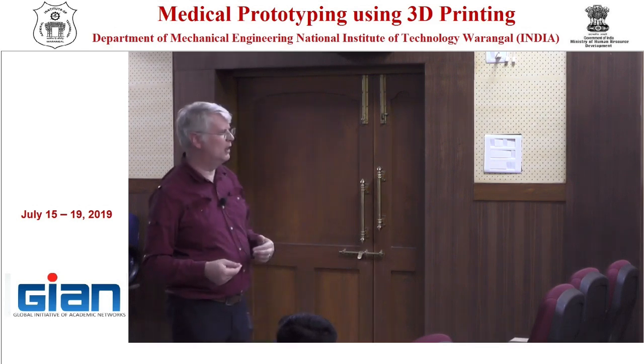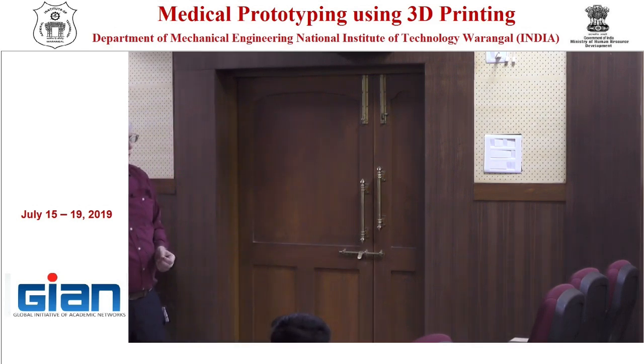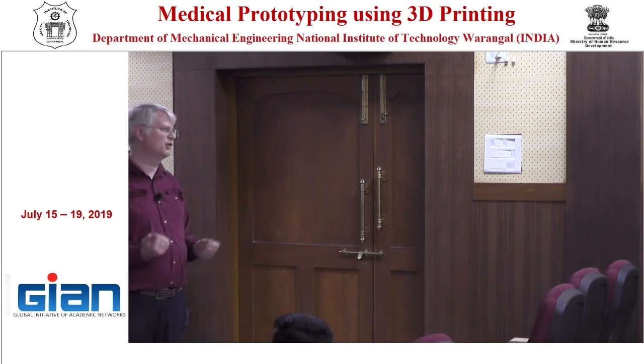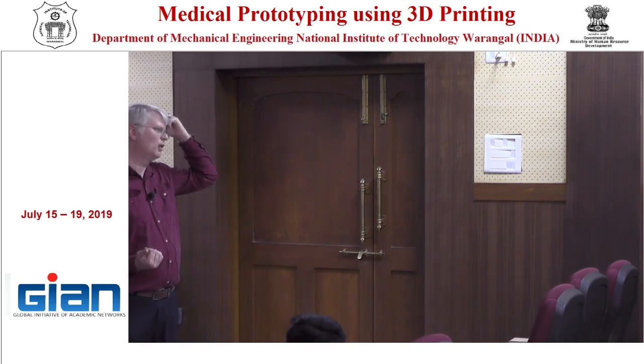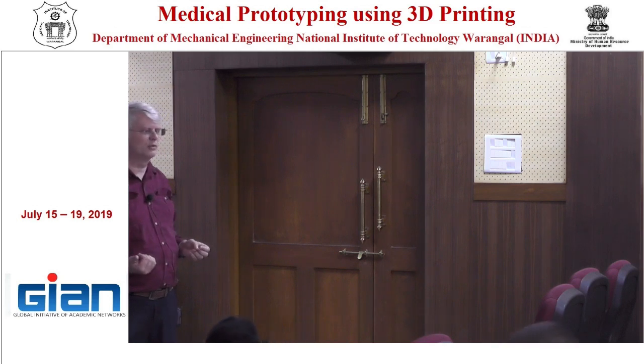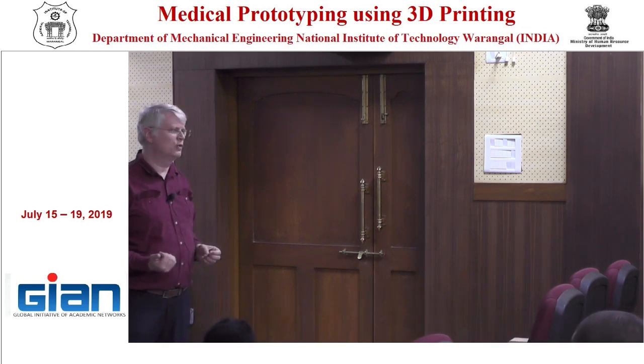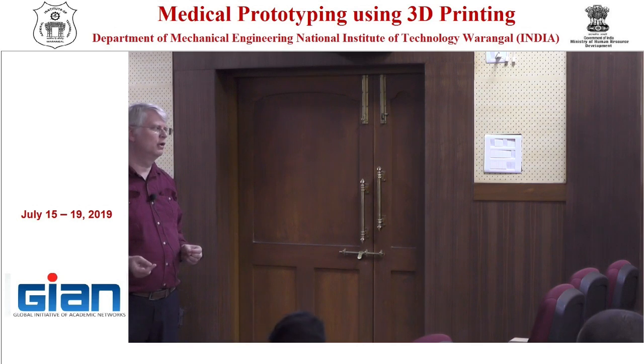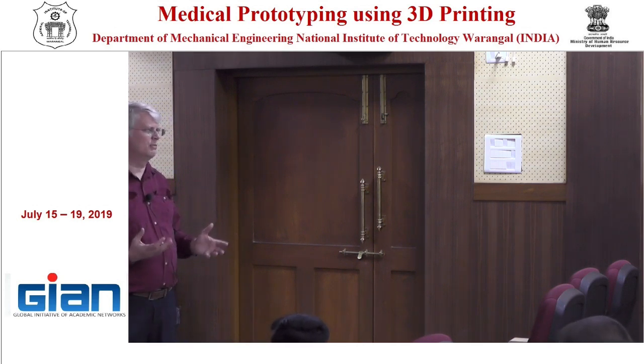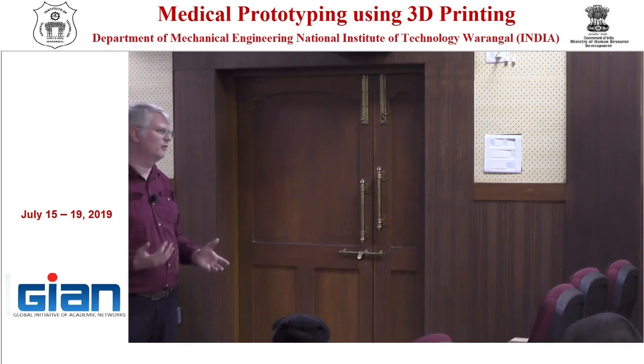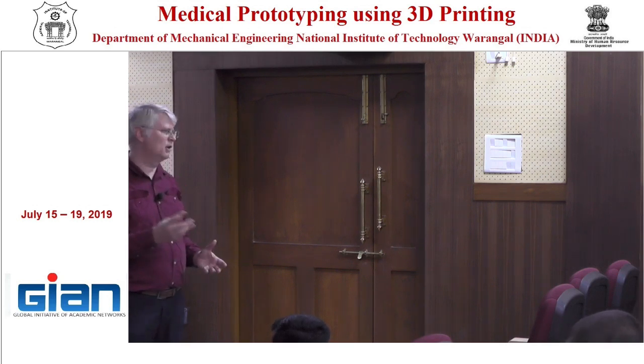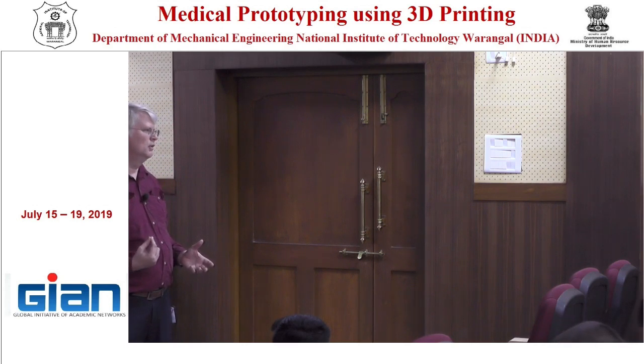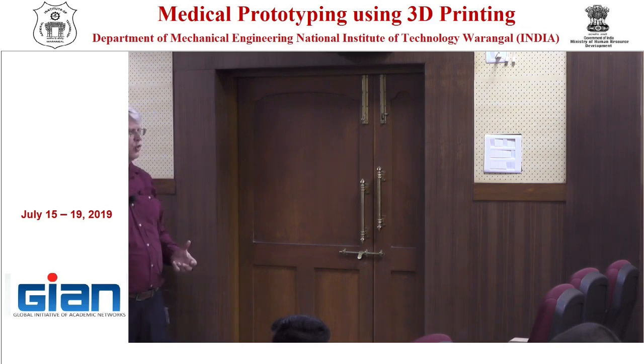Well, more than a day, quite often, to switch over from one material to another. If you have contamination, then yes, the most likely thing that you'll see is some weaknesses in the part. And they could be quite significant weaknesses. They could result in fracture surfaces. They could result in poor fusion at the site, because what you've got is a material which is melting at a different temperature, contaminating the material. So you then end up with unsintered material, so you get a void. That void can then turn into cracks.